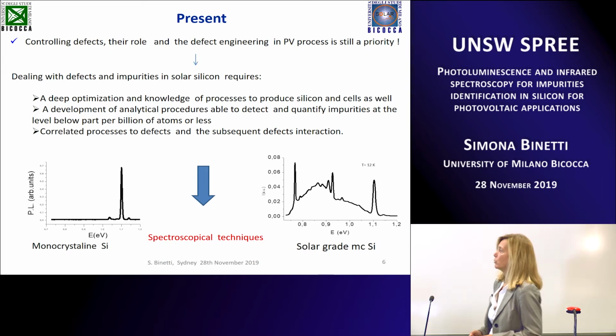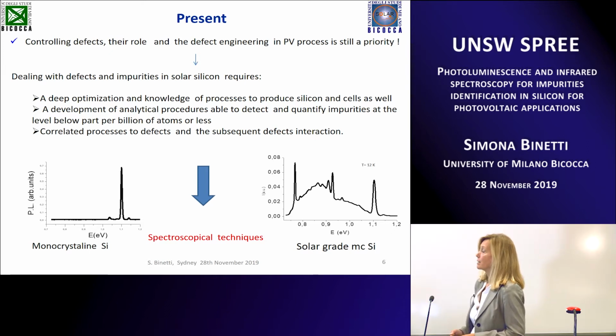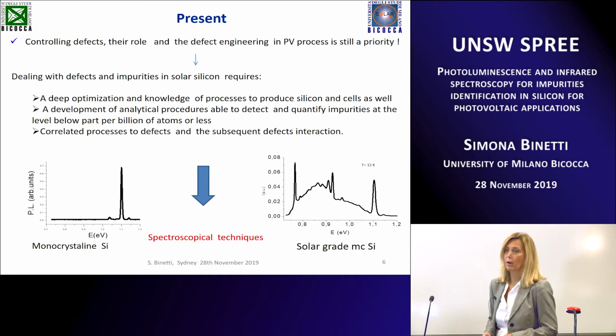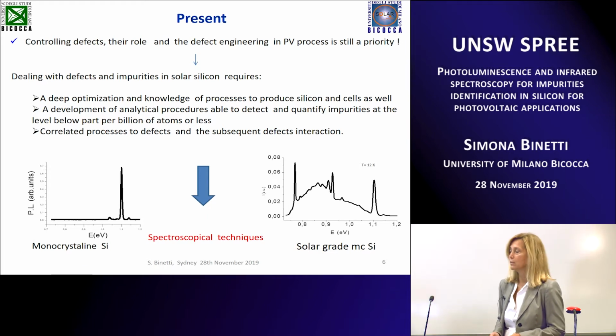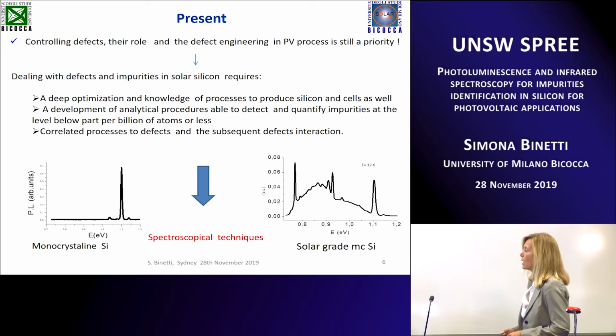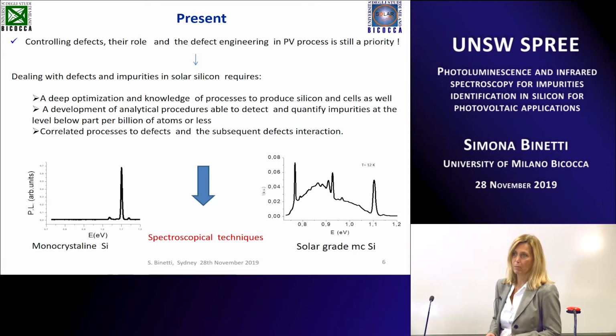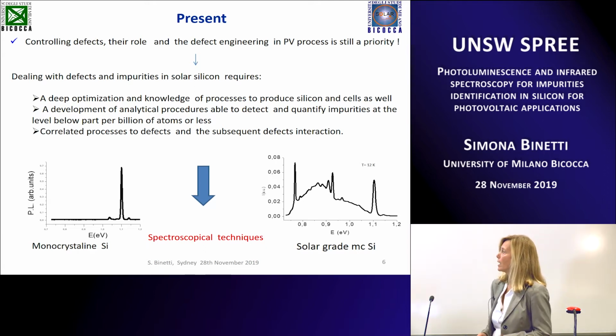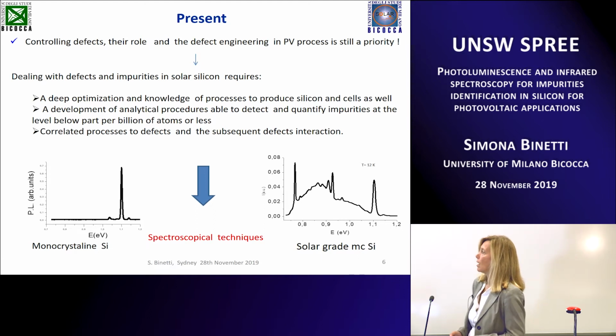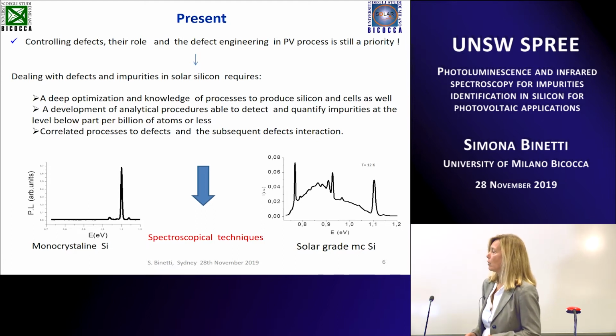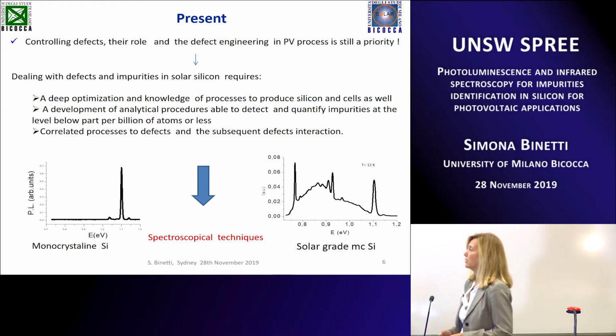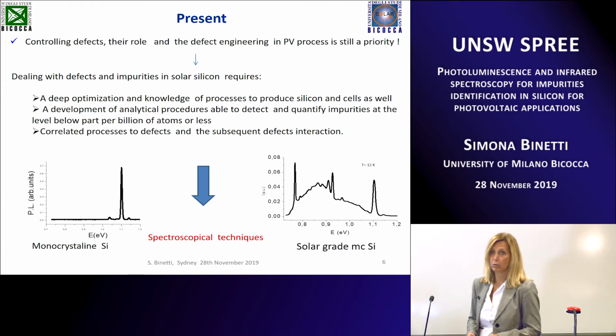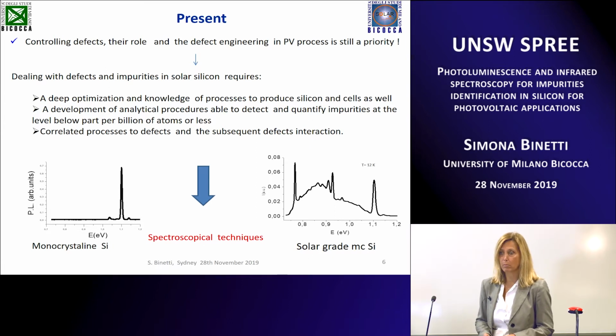I will try to show you during this presentation that by a simple photoluminescence or other simple technique like photoluminescence and infrared spectroscopy, it's possible to get a lot of information. You can see that by a comparison between two PL spectra, one collected on monocrystalline silicon, high purity, and the other collected on a solar grade multicrystalline silicon. You can see that there is a strong difference between them.